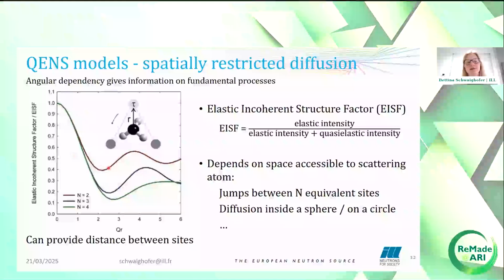For example, the EISF varies if you have 2, 3, or 4 equivalent sites available. There are also models for diffusion on the surface of a sphere, in a circle, or in a volume of a sphere. And therefore, fitting the EISF allows you to get information about the space accessible to the scattering atoms and distances between the nearest-neighbor sites or the radius of the sphere.